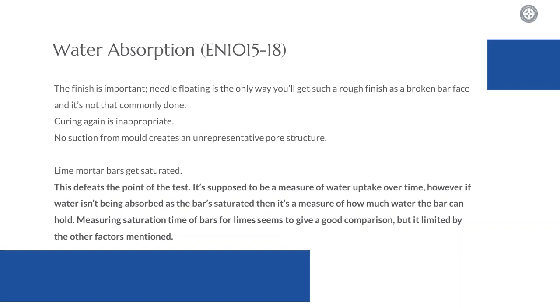A number of companies have actually started noting the point at which the bars are getting saturated, because at least it gives you a decent method for comparison between different mortars. What you can find is that you get to the end of a test and you can have two mortars which give you the same number, but one which is saturated in 20 minutes and one which is saturated in about 80 minutes. Obviously they do have quite considerably different water absorption rates.